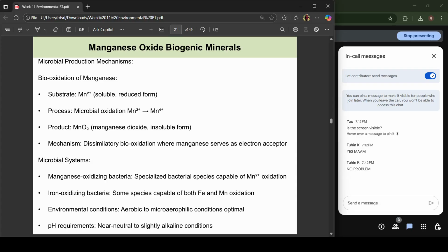So the mechanism, if you are going to describe here, it is going to be dissimilatory biooxidation, where manganese serves as the electron acceptor. In microbial systems, you have manganese oxidizing bacteria, and these are specialized organisms capable of oxidizing Mn2+ to Mn4+. And you also have iron oxidizing bacteria, and some of the iron oxidizing bacteria have the capacity to oxidize both iron as well as manganese. And the environmental condition required to produce this biogenic manganese oxide is that you need aerobic to microaerophilic condition, and the pH requirement is near neutral to slightly alkaline condition.